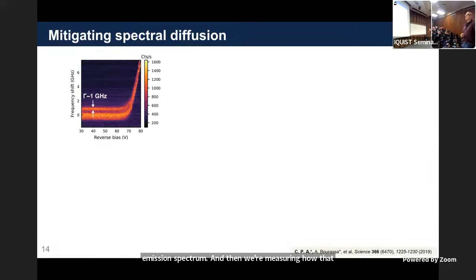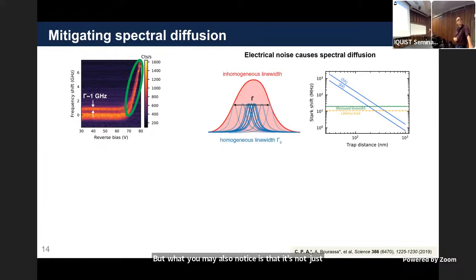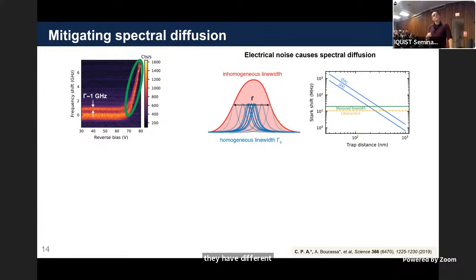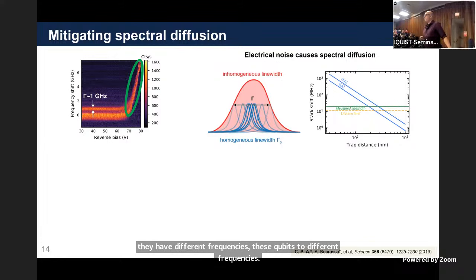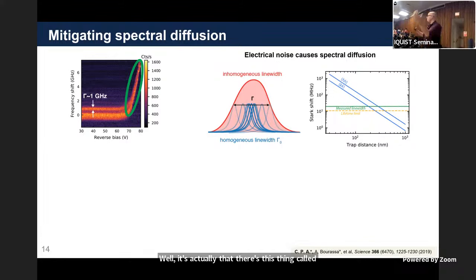Okay, so our goal was to Stark shift these emitters. This is one of those emitters I was telling you about, where at first you're applying voltage and nothing happens. And then all of a sudden it starts to shift. But what you may also notice is that it's not just shifting, it's also narrowing. And that's extremely exciting for these systems. Because the number one problem is not that these qubits have different frequencies, but that there's this thing called spectral diffusion, which is that semiconductors are noisy and there's electrical noise everywhere.